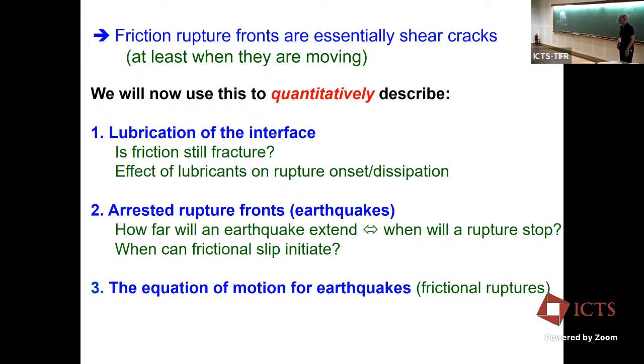Any other questions? Yeah. Is that kind of related to what you just answered? To what level can we treat these small contacts as continuum? Because I think that's what you just did. Yeah. Each pixel in my imaging has about 1,000 contacts inside it. The pixels that we have, it's our camera limitation, but it's about 100 microns by a millimeter or something. So we do see a statistical continuum. And that's what I'm describing as we talk about the crack tip. I don't have enough money to buy a 10 gazillion pixel camera that can take pictures at a million frames a second. I don't think anyone does, actually, but so we do it with Ken.